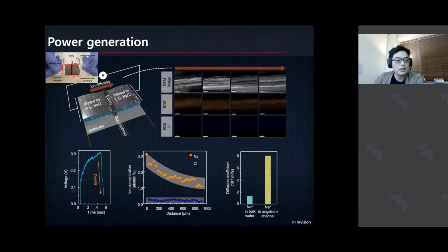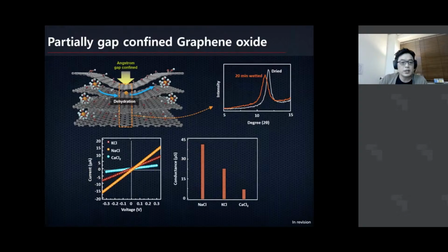And then this is the physically confined graphene oxide channel, and you build a high concentration reservoir of sodium chloride. Here's the low concentration of sodium chloride, and therefore your sodium cation is supposed to move in this direction. Your chlorine is not, because your chlorine size is bigger than the pore size of this graphene oxide. Also, it's a negative charge, so the surface repels the chlorine ion. Okay, so from high concentration to low concentration, only sodium ion is supposed to move. Okay, this idea works pretty well.